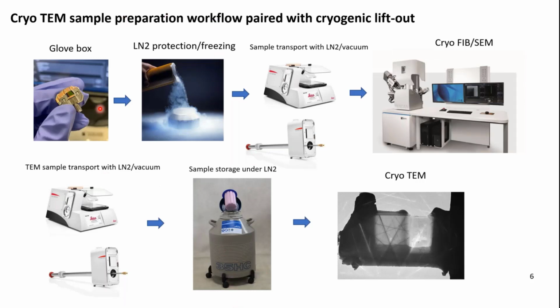Cryo-TEM sample preparation at cryogenic temperatures can be done in the following manner. We graphically summarize all this into one slide, but there are a lot of details in each step, so I will briefly go over this. When you first prepare TEM samples in your glovebox, we can plunge freeze your sample into liquid nitrogen. During this step, samples are stored inside a plastic bag before it is dunked into a liquid nitrogen bath to minimize air contact. And once your sample is in the liquid nitrogen, we cut the plastic bag in half to extract